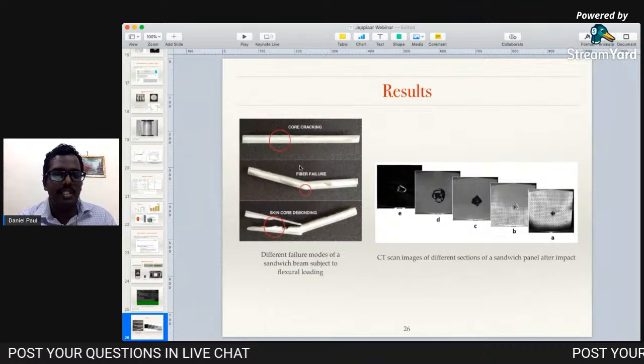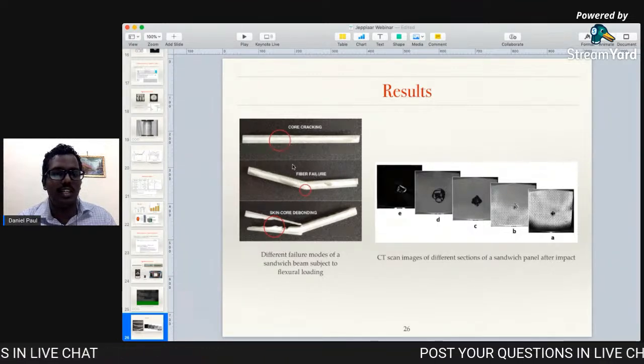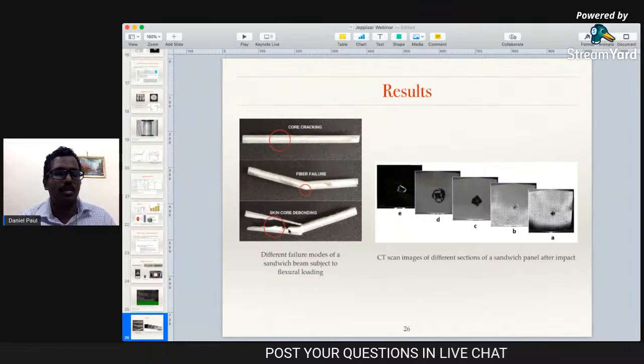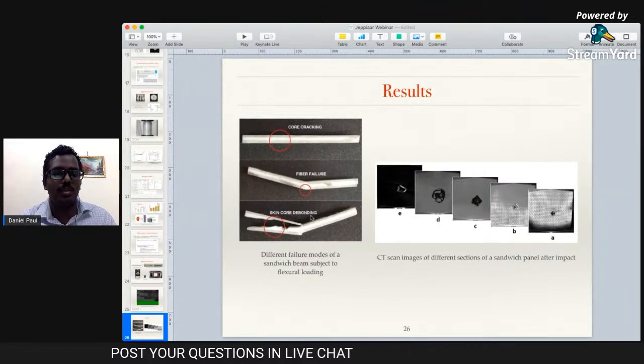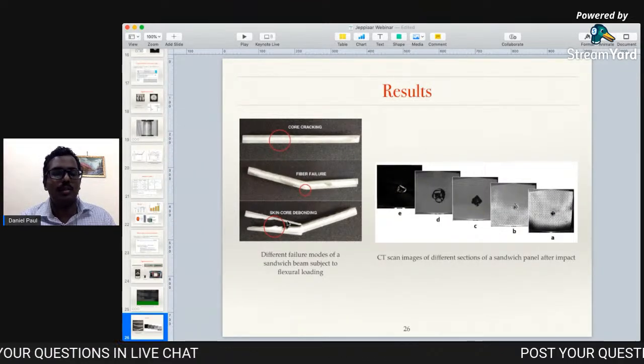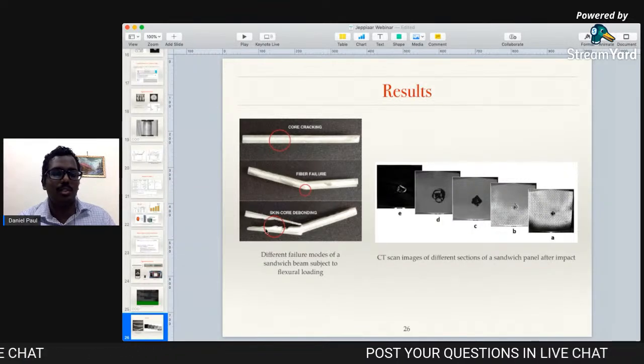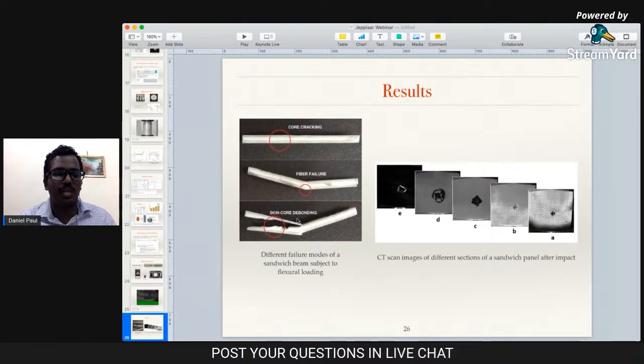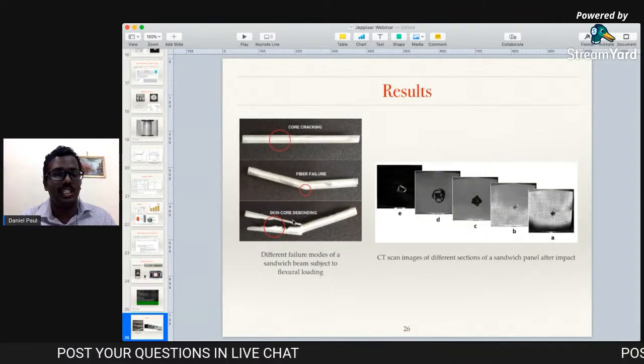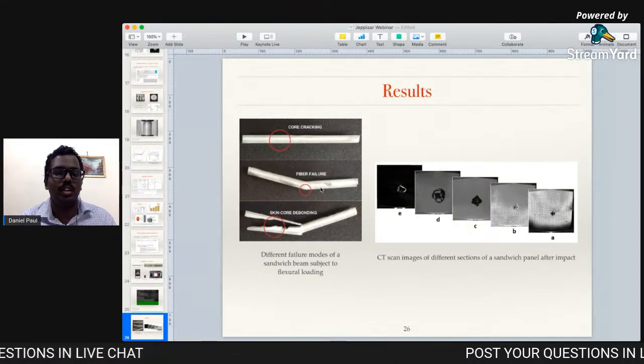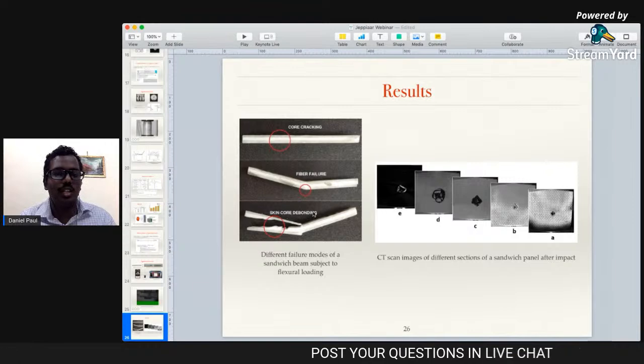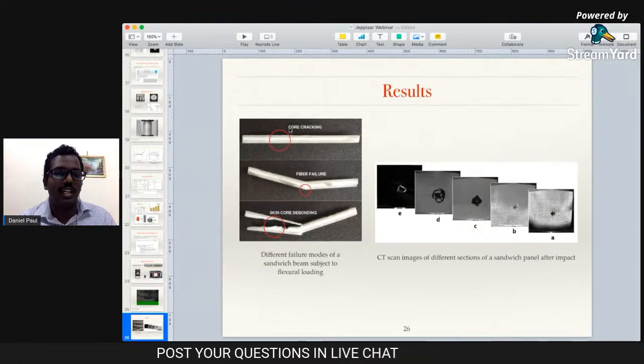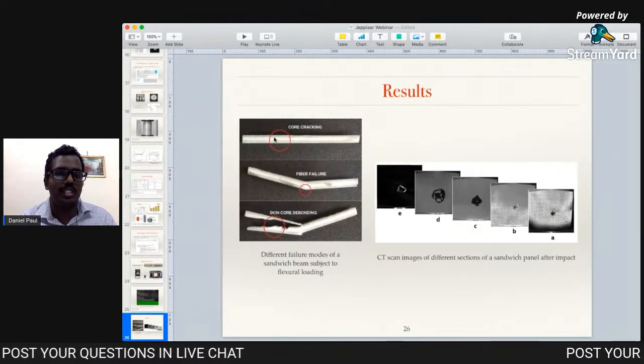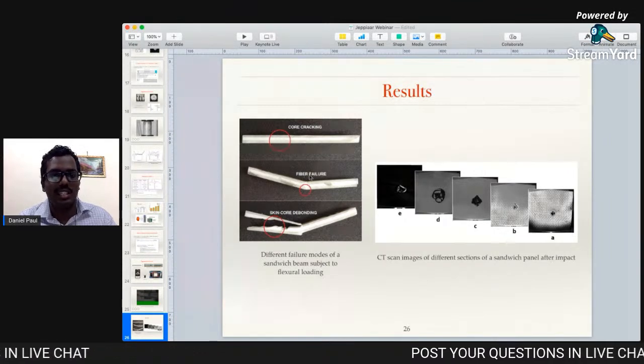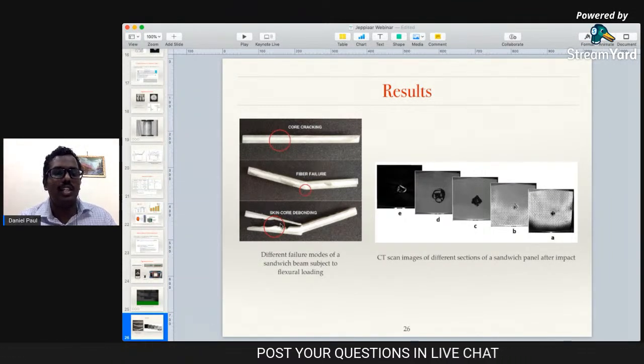And this is the result of the flexural test that we did. So if we have the skin and core separate, made of separate materials and then put them together, one of the major failure modes which was seen was skin core debonding. And this happened initially itself, but because of the co-curing method, we have delayed the skin core debonding, which causes complete failure. And so in our case, what happened is we had core cracking first, and then fiber failure, and then we had skin core debonding.